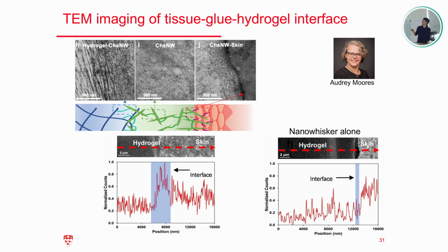actually, what we find is different. We have this nanoparticle actually forming a layer in between the hydrogel and the tissue. So at the end of the day, what we found in the TEM is the nanowhiskers form a condensed network sandwiched by the hydrogel and the skin. And this kind of network can not only penetrate into the hydrogel, but also, with the help of the ultrasound or the microneedle, it can penetrate deeper into the skin. So as I show here, we decorated our nanowhiskers using gold nanoparticles, and we really can see this high peak of this nanoparticle in between, penetrating both the hydrogel and the skin.